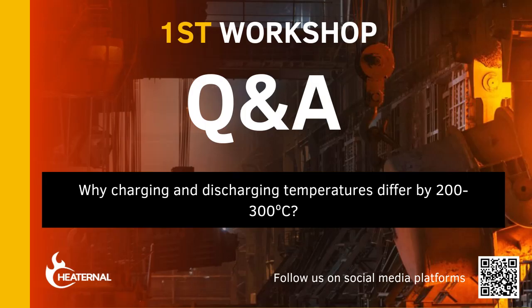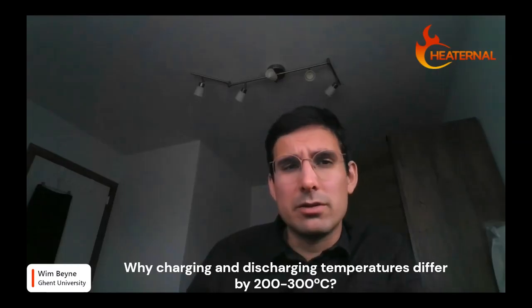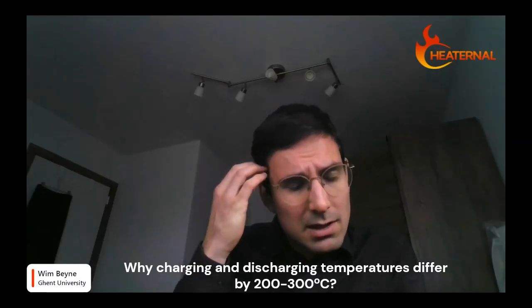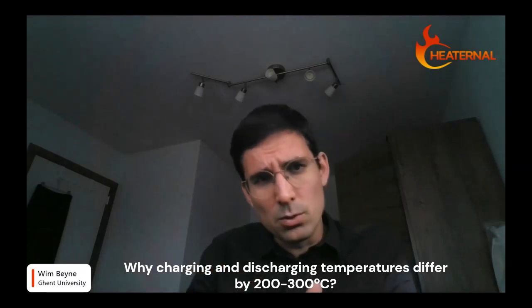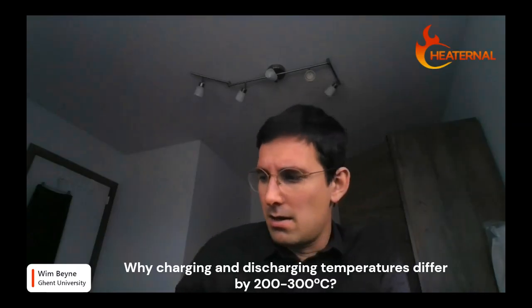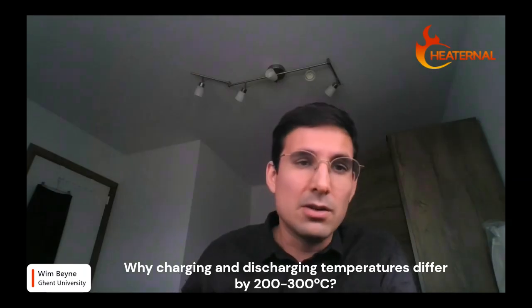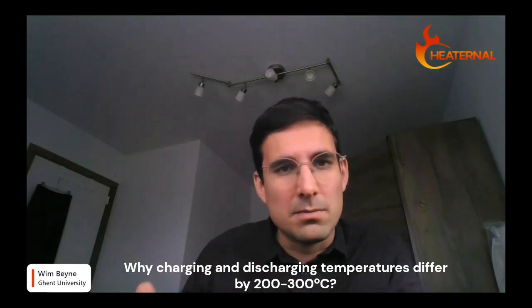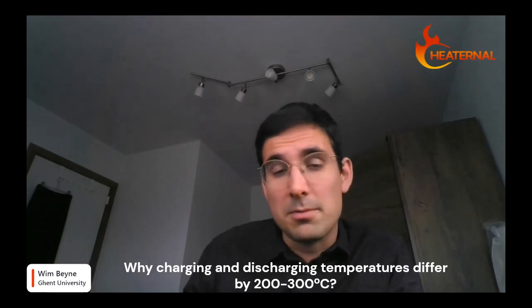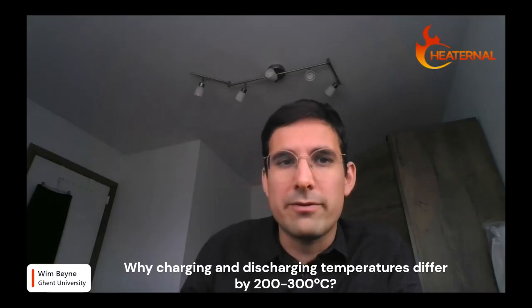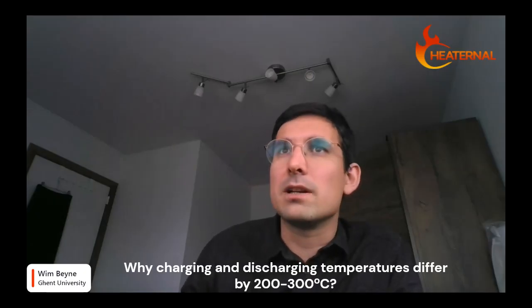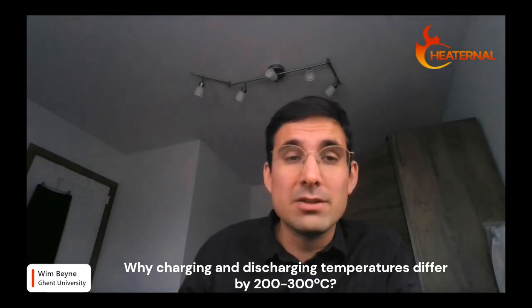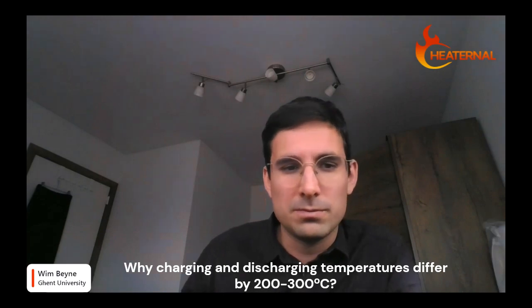Okay, thank you. The next question is why charging and discharging temperatures differ by 200 to 300 °C. Yeah, I think I can answer that question. These are representative values for one of our use cases. The 780 degrees C was representative of a furnace, waste heat essentially coming out of the system. And then 480 is preheated air, which you do the final heating with the system. So these temperature differences are quite large, but it is what we found for the use cases. And I think it is something which is specific to the high temperature industries, that you have these higher temperature differences. Hope that answers the question.